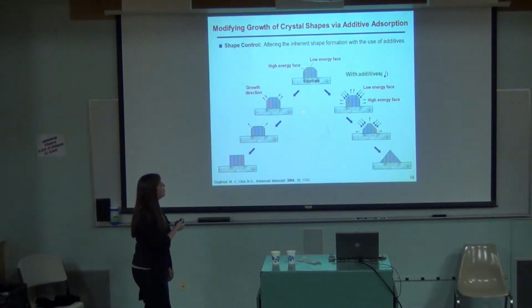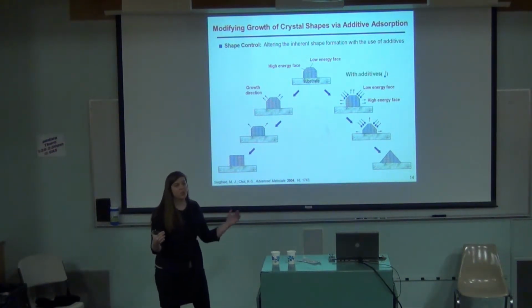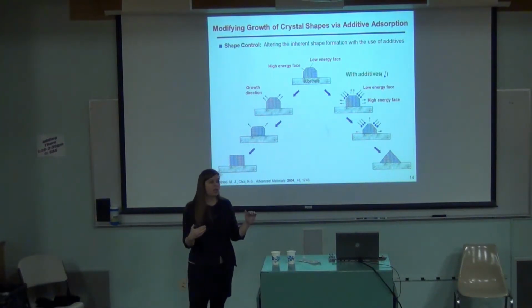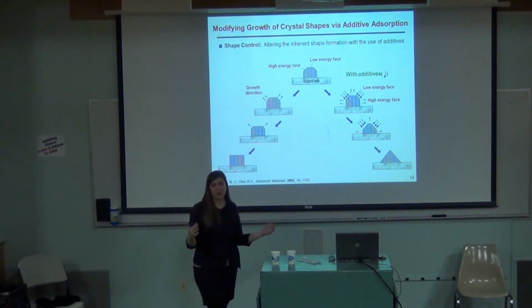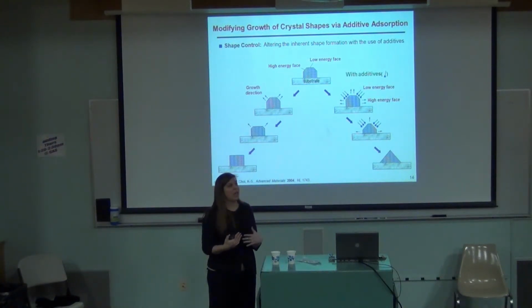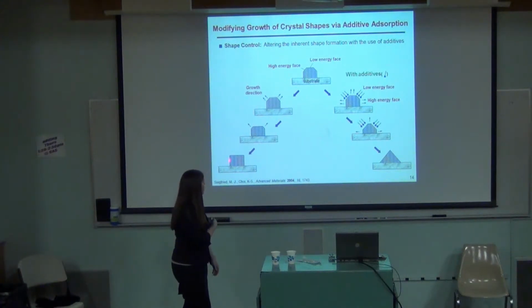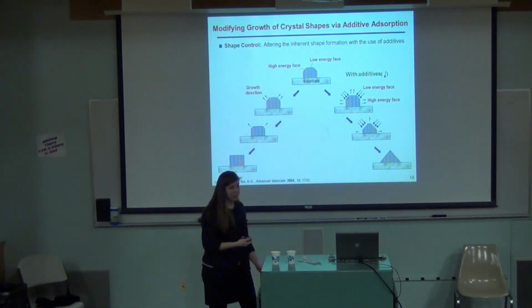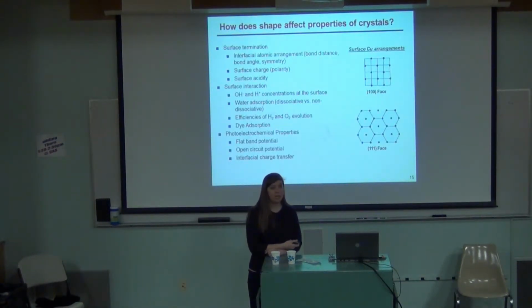So we studied the mechanism of why this happened, and we believe that there's a high energy face and a low energy face. And the way that it grows is it grows due to the higher energy face growing out of existence. So you can put a barrier on your crystal, which really isn't a barrier, it's just in solution with your other materials, and you can change the high energy and low energy face, which means that instead of it growing to be a cube or a rectangle, it grows to be an octahedral or a triangle shape. And so I'm going to show you that you really can do that.